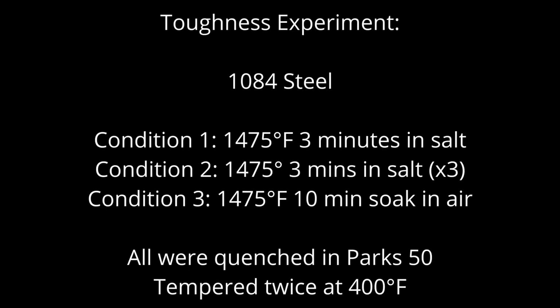But the real question is, can we get improved toughness with the rapid heating and short soak times that we can do in a salt pot? For this experiment, I used 1084, and I did a 3-minute hold at the 1475 before quenching in Parks 50 and tempering at 400 degrees. I compared that with a normal heat treatment in my conventional furnace in air for 10 minutes with a true 10-minute soak time at the same temperature of 1475. And then I did another experiment in the salt pot where I put it in for 3 minutes at 1475 and quenched, and then I did that 2 more times for a triple quench, followed by the 400 degree temper.